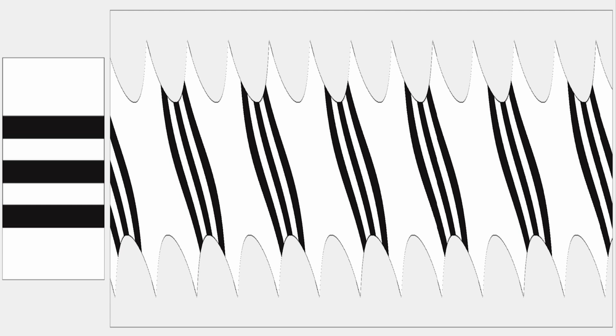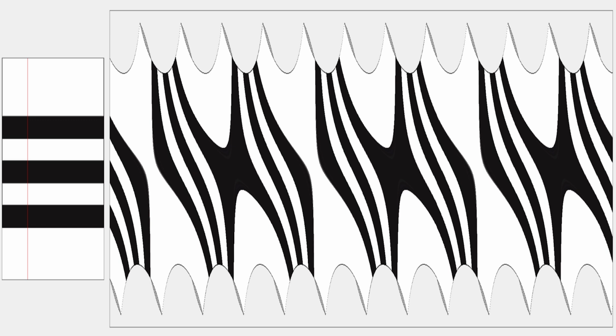We now have the proper dimensions and distribution of layers in the original billet that was used to create the chevron straight section of the blade. The 2 thicker top and bottom white layers combine to form a twice as thick white layer in the twisted billet that has the same rough dimensions as in the original blade. Notice that some sections of the chevron pattern show just a 5 to 10% grinding, but others go deeper to about 25 to 30%. This image is just a visual reminder of what the 25% ground off looks like.